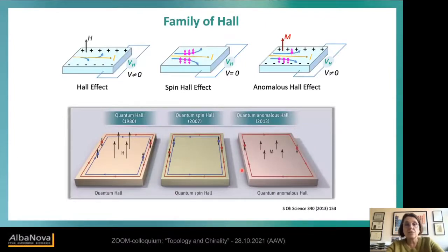The whole story should be understood, as I mentioned before, in the context of the quantum Hall effect. So I want to remind you, this is a nice draft. The quantum Hall effect was a two-dimensional electron gas. So you simply can think about electrons in two dimensions, forget what the real material is. This is not so important. And if you apply a very high magnetic field and go to very low temperature, edge states were observed. You saw already for the topological insulators, electrons where the spin and momentum were locked; in these two-dimensional electrons, it was simply at the edges of the material for both spin directions. In the topological insulators, you have the crystal, and it's all over the crystal.